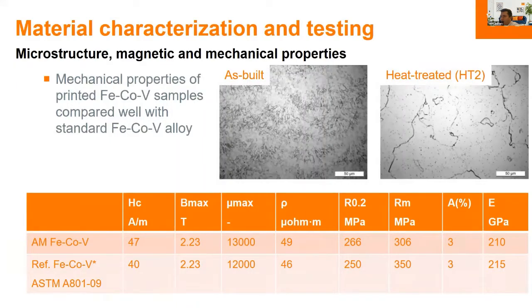Then after the optimization of those microstructures, you are ready to move to characterize the materials. In our case, we have looked at the microstructure and how it is affecting magnetic and mechanical properties. And in the case of standardized alloys, of course, it's nice to compare the results to the standardized alloy properties. If you have a totally new material composition, of course, it's much more difficult to see how close to the optimum you are. But this is one example: after quite heavy optimization work on first the additive manufacturing process parameters, and after that the heat treatment cycles, we have finally achieved almost the same magnetic and mechanical characteristics as the standardized iron cobalt vanadium alloy.